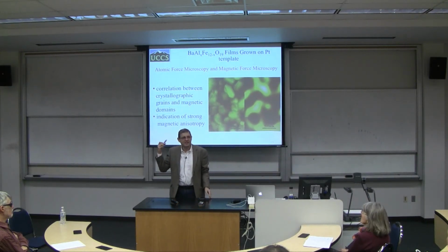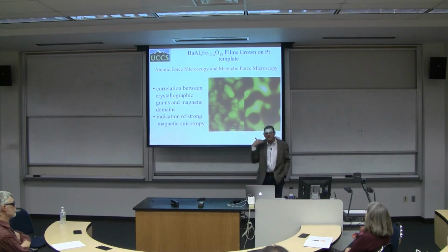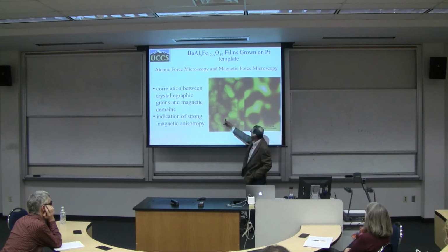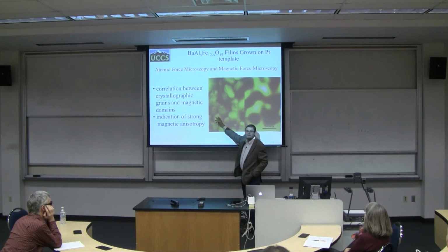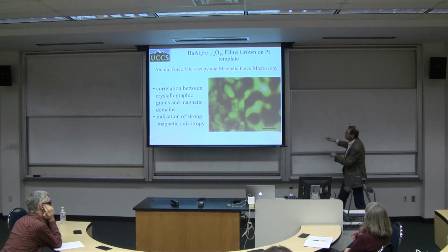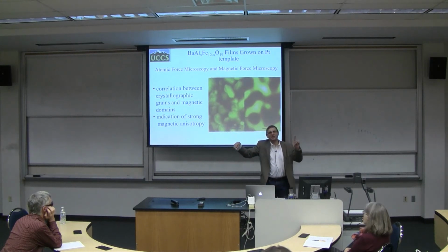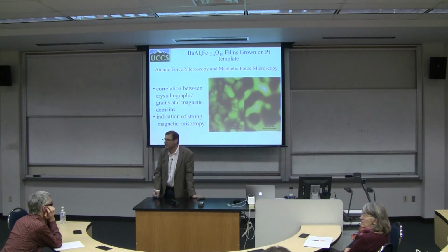In stuff like this, the anisotropies are so strong that within a given grain, I never have a domain wall, because anisotropy simply prevents them from forming. But if I have two independent grains, like this one and this one, when they demagnetize, in other words, this picture here, when one grain is up, this one can be down, because it doesn't cost the system energy whatsoever. So this is why this is happening.